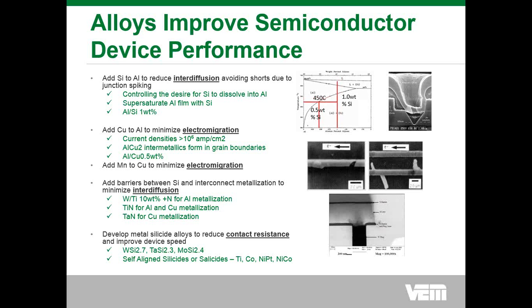And the challenge here is, how do I reduce the contact resistance between, let's say, tungsten and silicon and tungsten and aluminum? And therein, the industry has moved to the development of metal silicides. These are things like tungsten silicide, tantalum silicide, moly silicide, to reduce contact resistance. Furthermore, we've moved further along to the use of what are called self-aligned silicides or salicides. And here people use titanium, cobalt, nickel, platinum, and in most advanced applications, again, we're looking at an alloy of nickel plus cobalt.